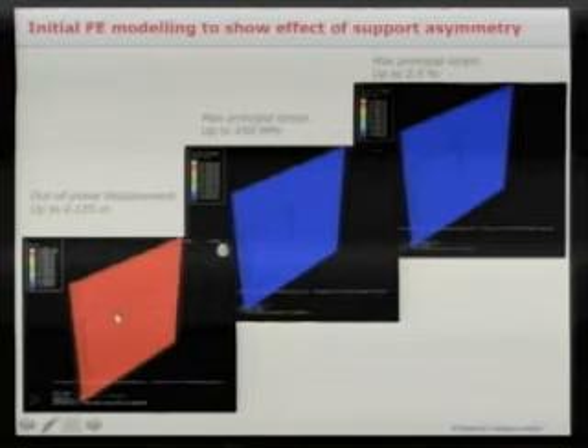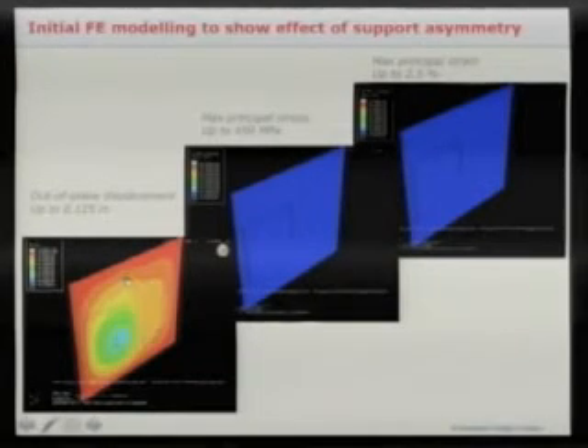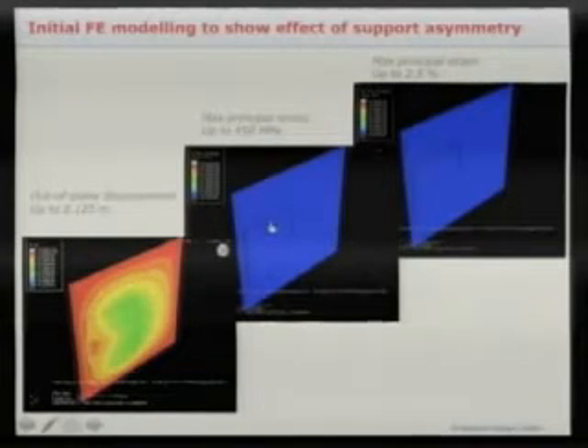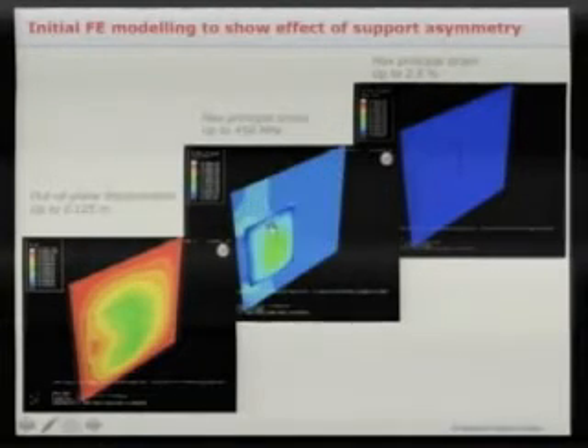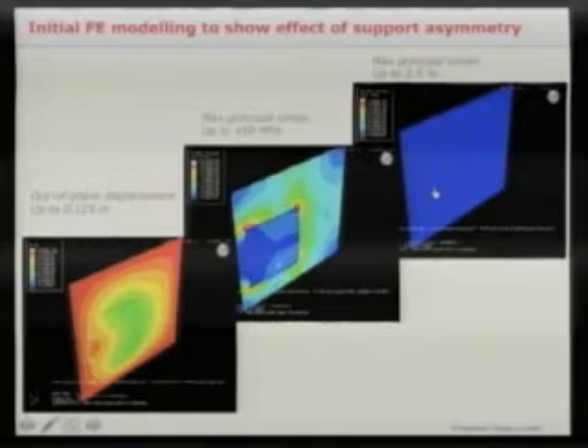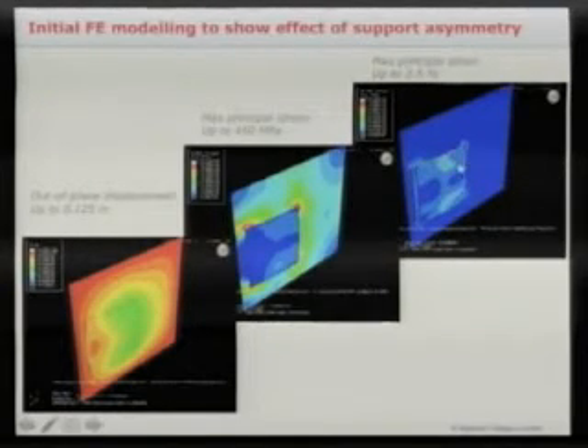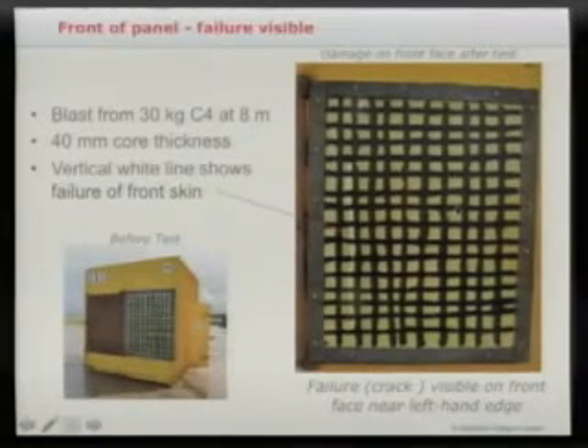So when I play that, you can see here the displacement of the composite panel, but also some displacement of the steel front of the cubicle. That in turn affects the stresses and, of course, the strains, and that's the strains which ultimately drive the failure process and cause the cracking to occur down this right-hand edge. And here you can see the damage for the worst case. So you've got a crack which is running from this corner down this edge here. This is very typical of these panels when we test them.